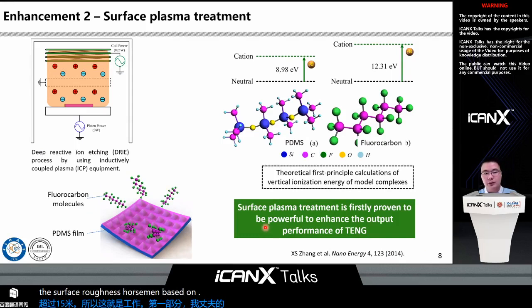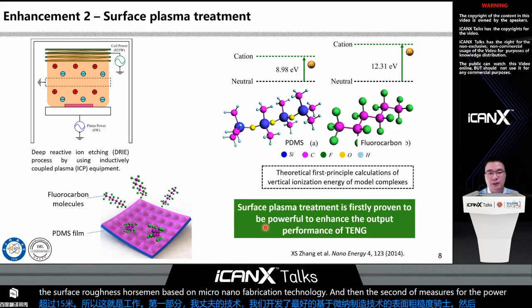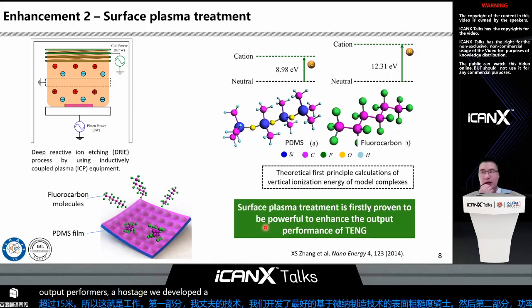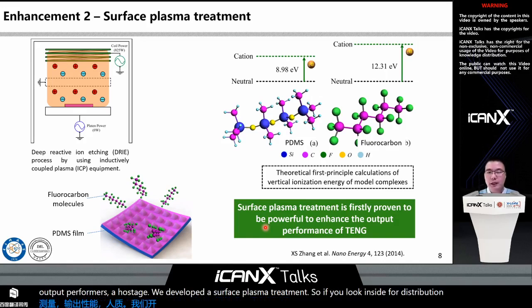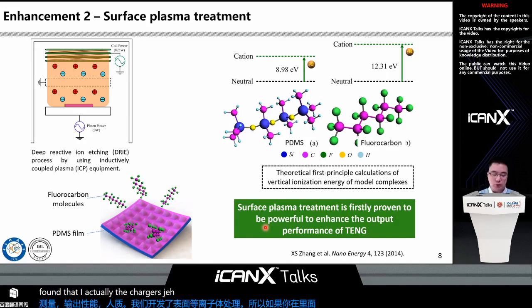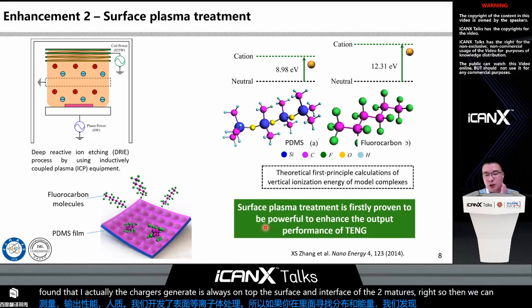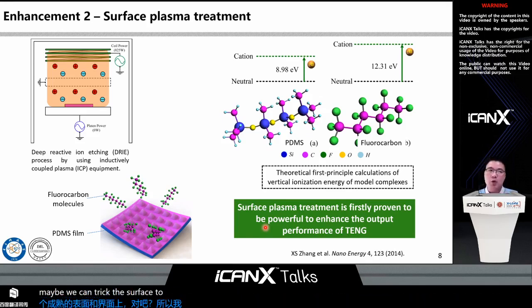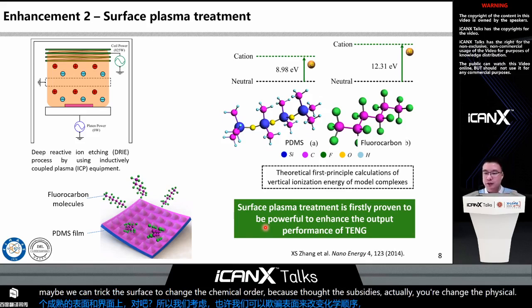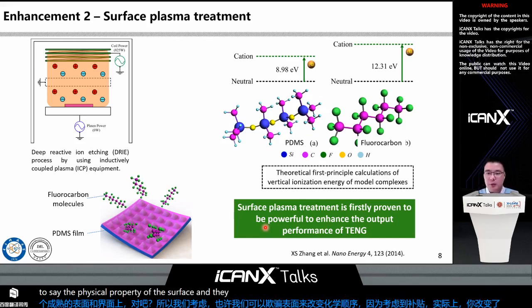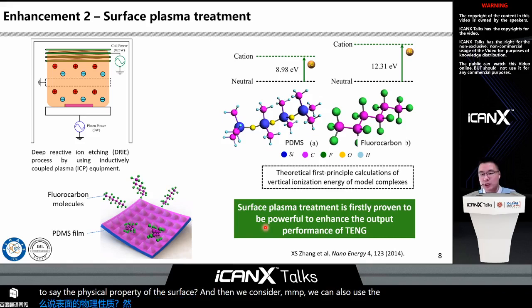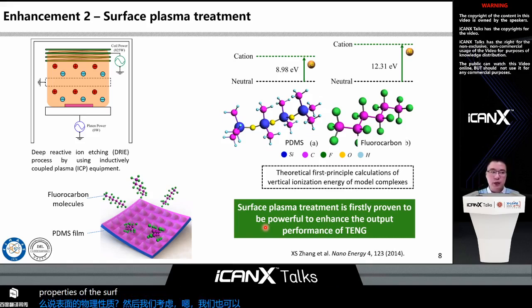And then the second method for the output performance enhancement we developed is the surface plasma treatment. If you look inside this triboelectric nanogenerator, we have found that actually the charges generated are always on the top of the surface at the interface of the two materials, right? So then we considered maybe we can treat the surface to change the chemical properties, because surface roughness actually changes the physical property of the surface. We considered maybe we can also use some technology to change the chemical properties of the surface. In this way, we maybe can also enhance the output performance of the devices.